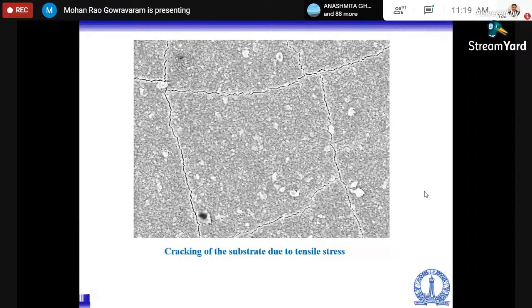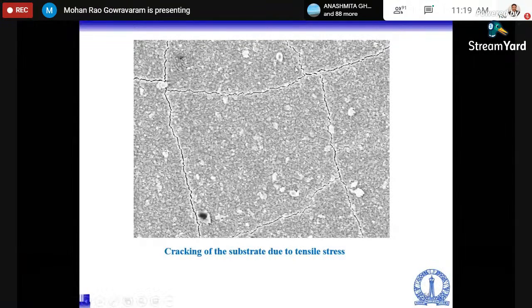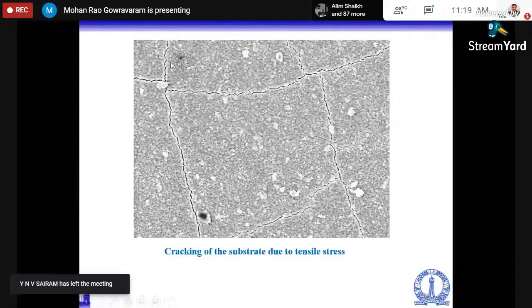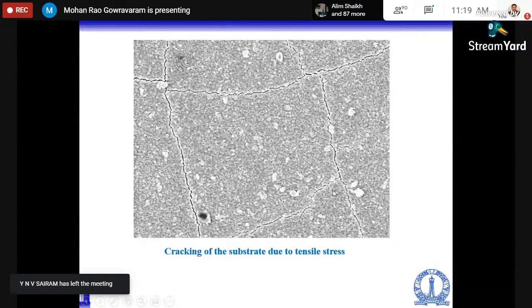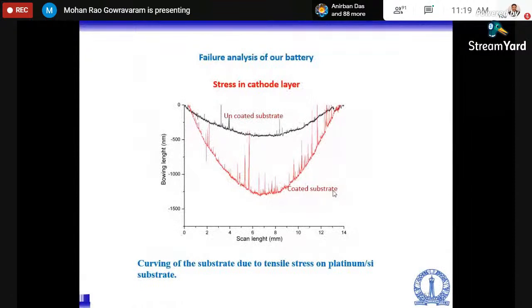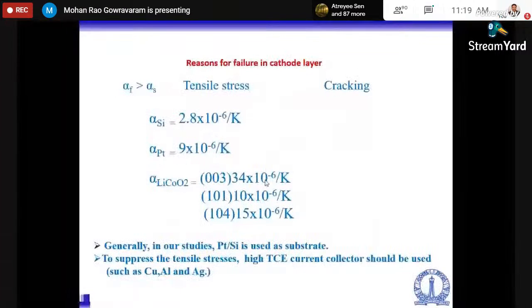Now, in the lithium cobalt oxide, after a few cycles, what we have seen is that there are a lot of cracks like this that have been formed. So now you try to analyze why these cracks have come. Now, this is due to the stress in the cathode layer. Now, the curvature of uncoated substrate is the black one that you see. And after coating, because of the stress, the curvature has increased. So this much of tensile stress is there in your deposited film. Now you try to analyze what could be the reason for the stress.